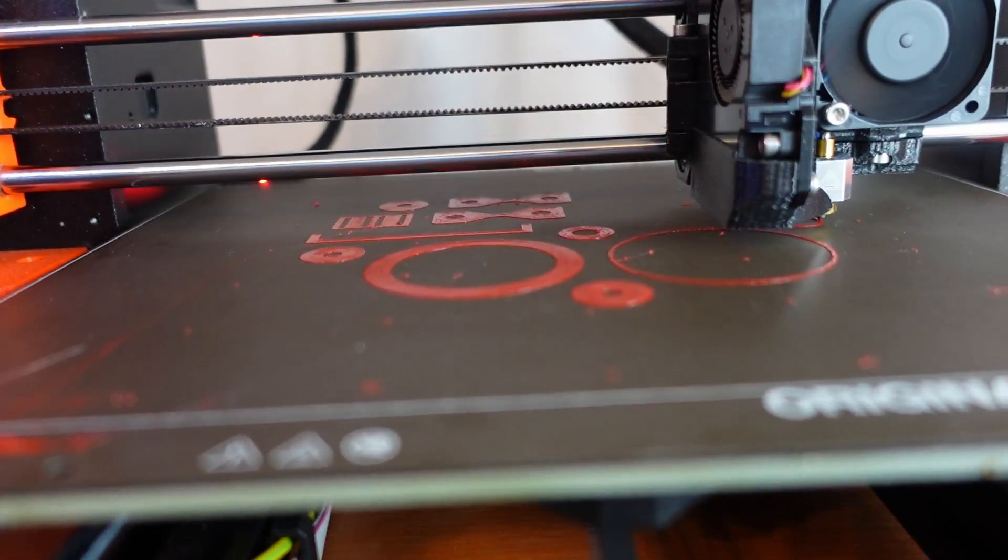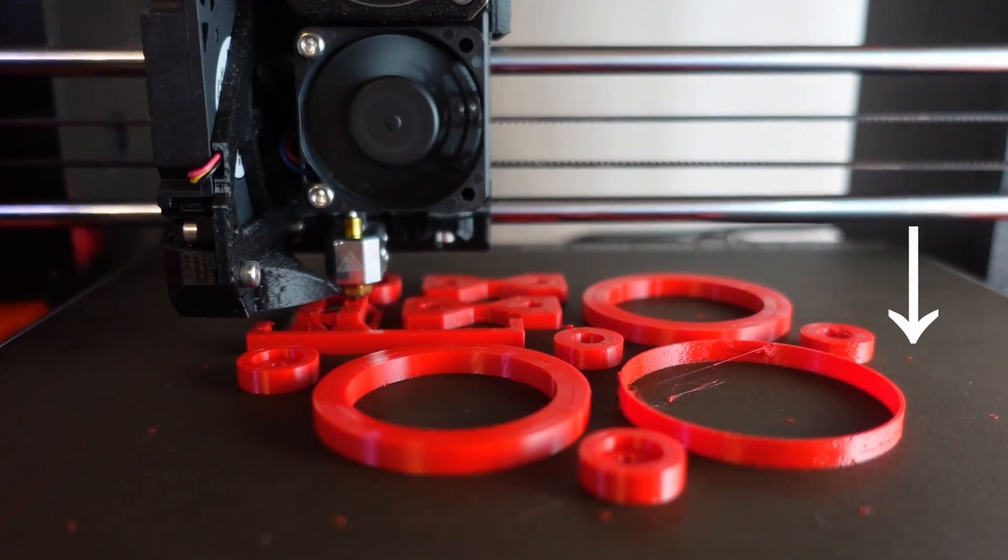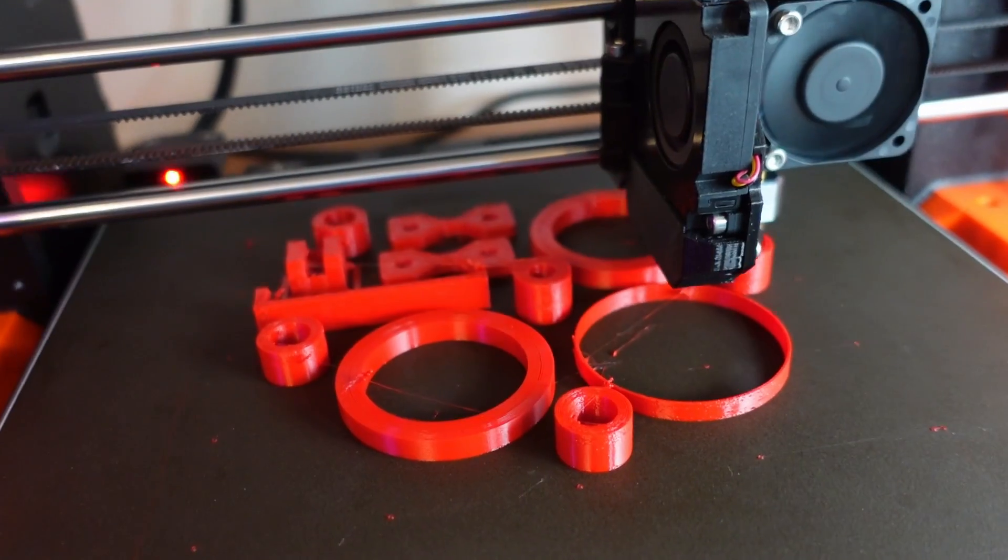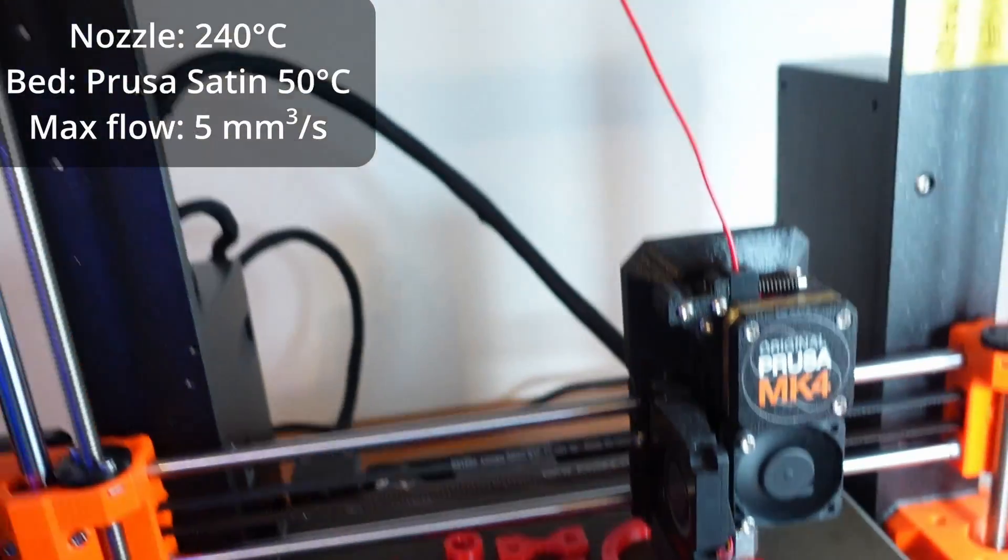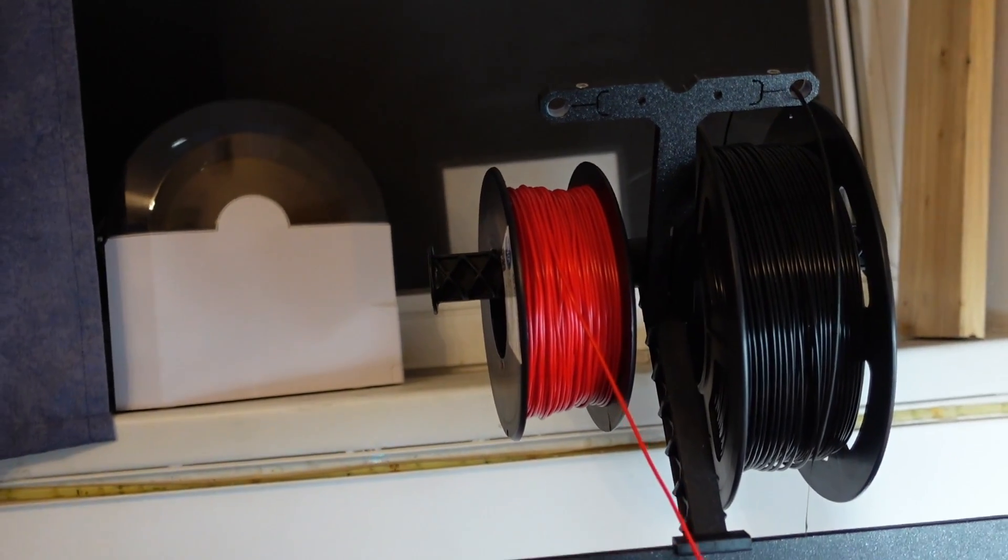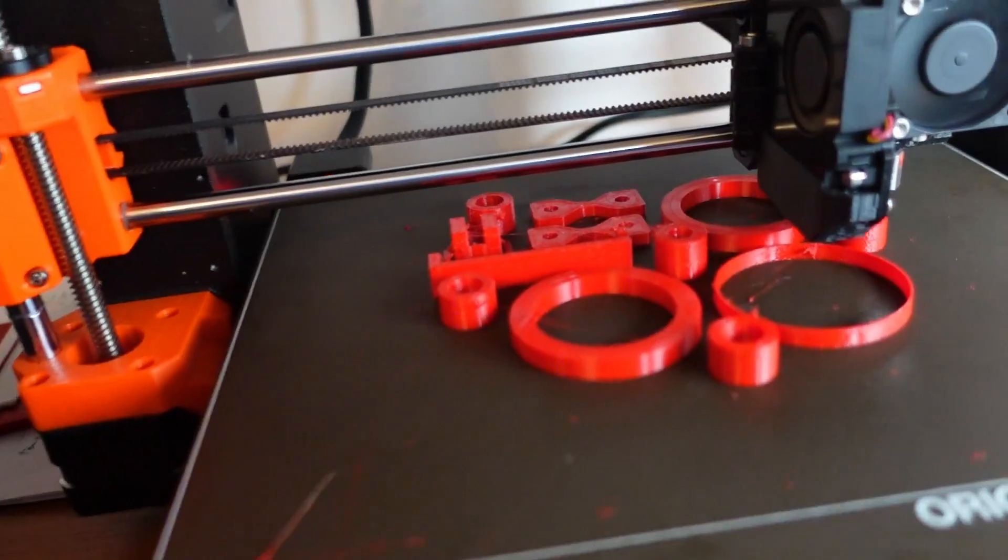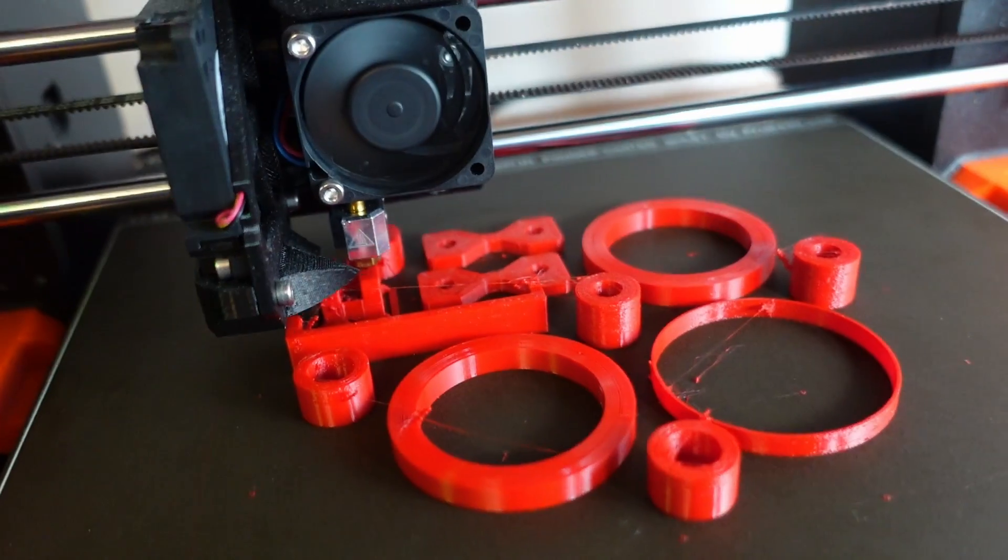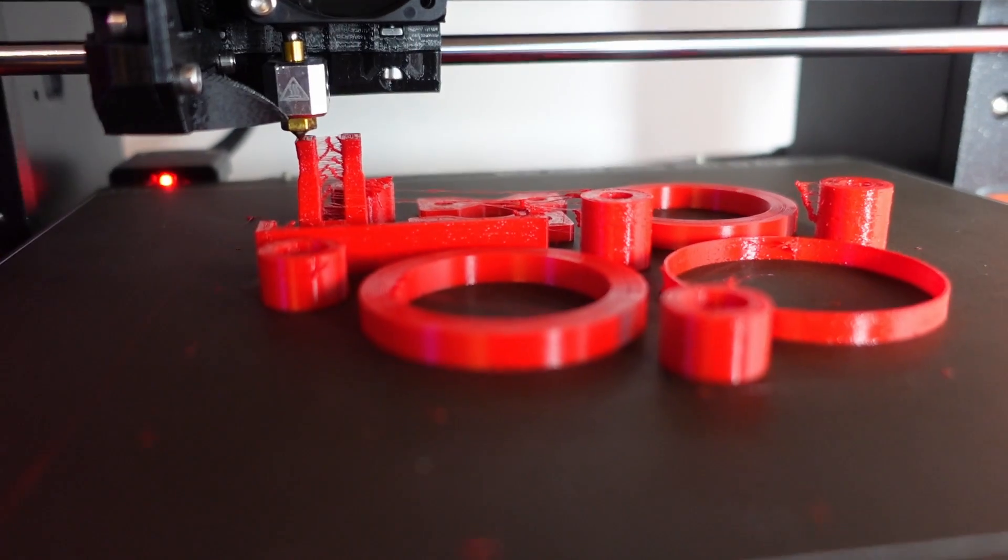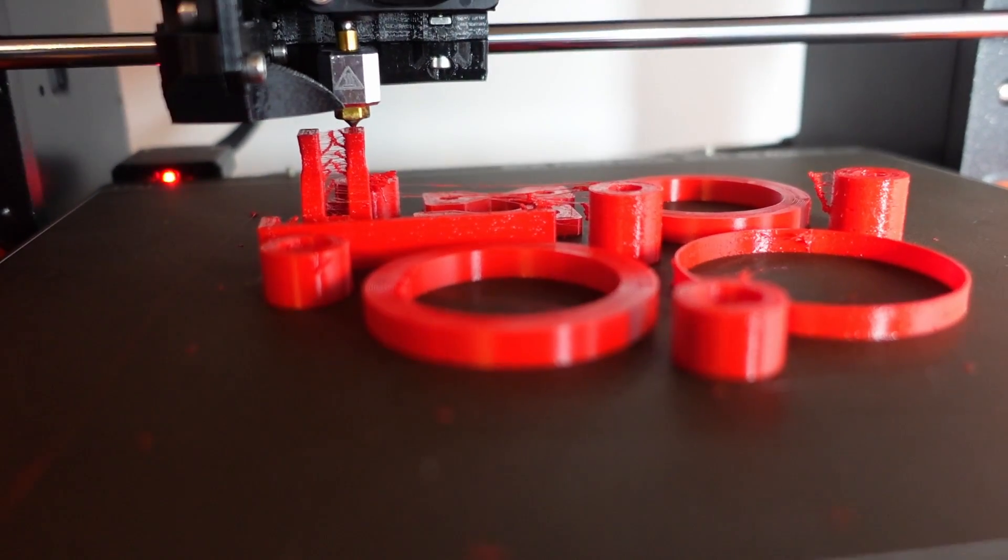This is the first layer and those small spots are actually from the nozzle touch during the auto leveling. And this was quite long printing, 3 hours. After 2 to 2.5 hours I noticed that some stringing appeared because I am printing from the open air, not from the filament dryer unfortunately. And this stringing just became a little bit bigger on those last 2 elements for the layer adhesion.